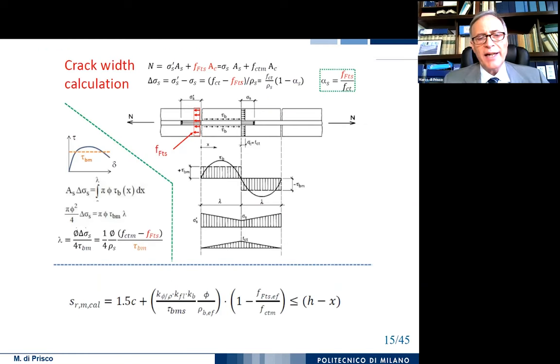When we compute the crack distance, we have to take into account two main contributions. Of course, in the equilibrium, we have to take into account the residual stress on the cracked section. And we also have to compute the stress in the bar, which is changed because the residual stress is guaranteed by the presence of the fibers. And we could also evaluate a change in the tangential behavior, so the bond, the stress versus slip behavior of our bar. But usually, this final contribution is neglected to simplify the approach.